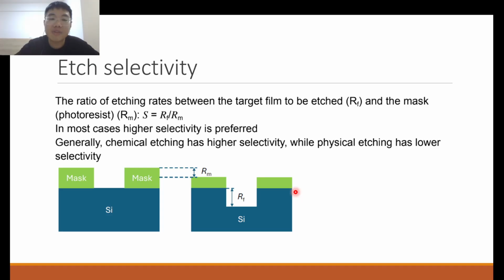And so your selectivity for your material must be greater than your selectivity for the mask. If not, let's say you want to etch a 5 nanometer deep trench and your mask is only 3 nanometer thick. If you etch your silicon at the same rate as your mask, by the time you etch 3 nanometer in your silicon, not even reaching your desired dimension yet, your mask is gone. It's all eaten away already. That's not good. So of course we want an etch that has greater selectivity for the thing you want to etch and less selectivity for the thing you don't want to etch.